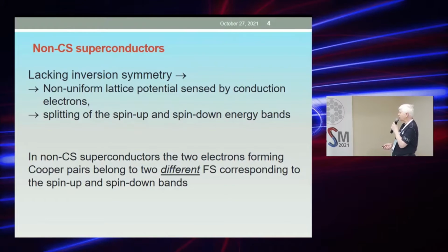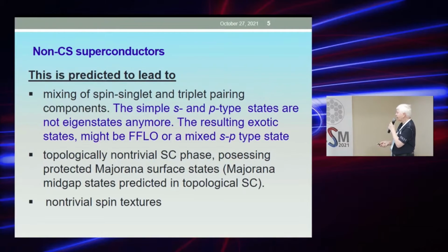When you have inversion symmetry lacking, then the non-uniform lattice potential, which is sensed by conduction electrons, splits the spin up and spin down energy bands like a Rashba effect. And the two electrons forming the Cooper pair become belonging to different Fermi surfaces corresponding to the spin up and spin down subbands. And this may lead to quite interesting consequences, predicted mixing of the spin singlet and spin triplet pair components. The resulting exotic states, according to theory, might have a different mixture.